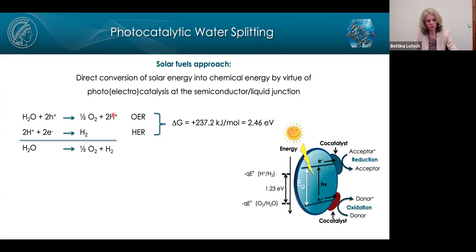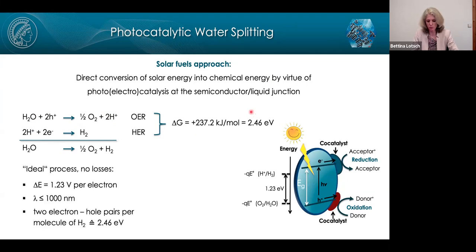So water splitting is composed of two half reactions, the water oxidation reaction and the water reduction reaction, or hydrogen evolution. And it is a thermodynamically uphill reaction by 2.46 eV. How do we arrive at these 2.46 eV? Well, basically, in order to produce 1 mole of hydrogen, we need 2 energetic electrons, energetic by 1.23 eV. So that needs to be the size of the band gap, the minimum size, if we assume an ideal process without any losses. And that corresponds roughly to a wavelength of below 1000 nanometers. 2 of these electrons then give us 2.46 eV.